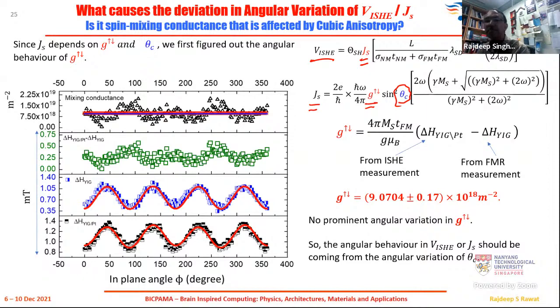So it's basically something which controls the spin transport property across the interface. So it's a very important parameter and needs to be quantified and understood. And the second is the precession cone angle. If you look at the spin mixing conductance expression, it is basically the difference of the linewidth measurement for the YIG/Pt sample as opposed to the YIG linewidth of the pure YIG sample. And we have these two values which are shown over here and here. If you take the difference of these two, this is the mixing conductance.